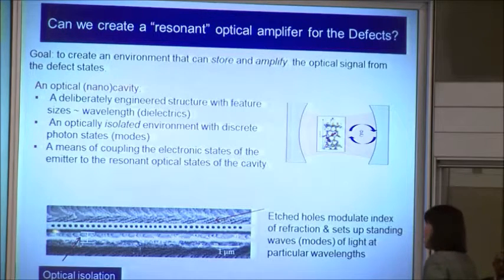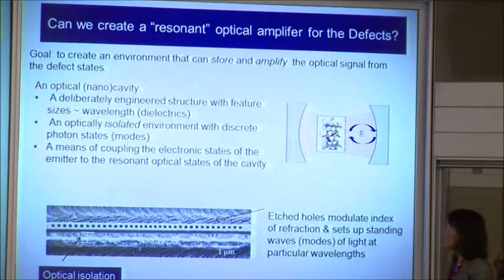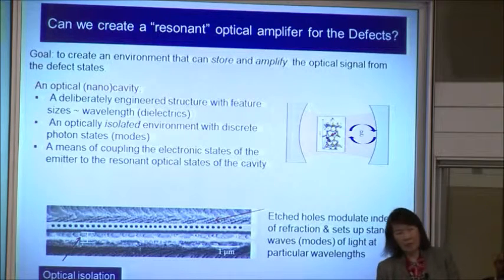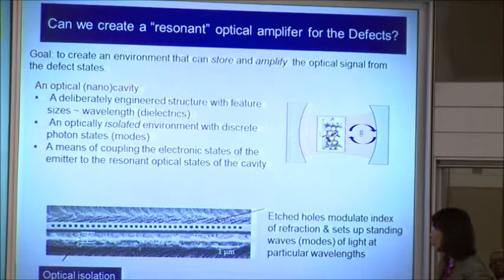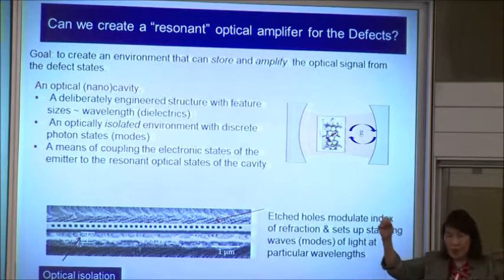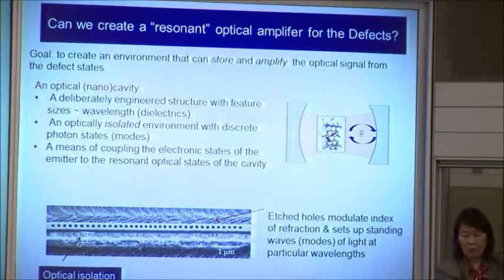This is a narrow bridge of silicon carbide. This is 1 micron. So this feature is about 200 nanometers in width. It's several microns in length, and there is a reason for this particular design. It is optically isolated from the substrate. You can't quite clearly see it, but it's a suspension bridge that's held over a substrate. And the most important feature of this nanobridge are the holes.